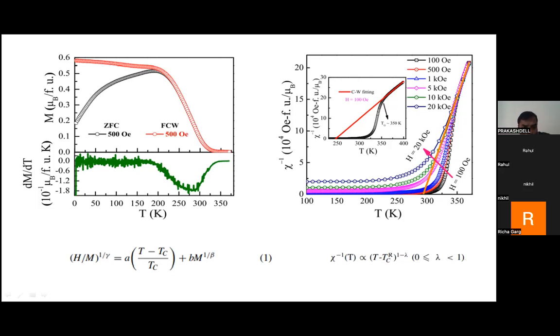Even at 274K, in principle your magnetic moment should have been zero, but it is not. It will be exactly zero at 350K or well above that. In this region, 274 to 350, there are some clusters or local regions where interaction among a very few spins does exist, and long range interaction among them has set up this critical state.